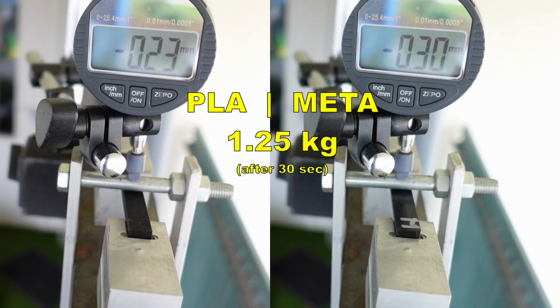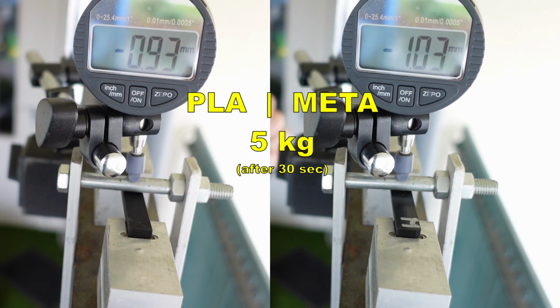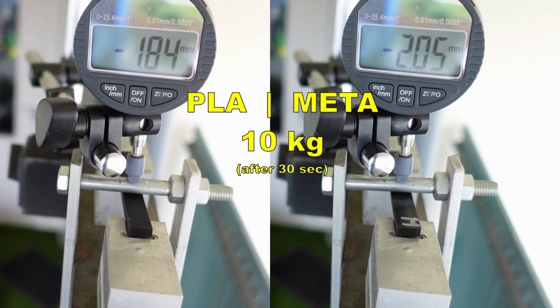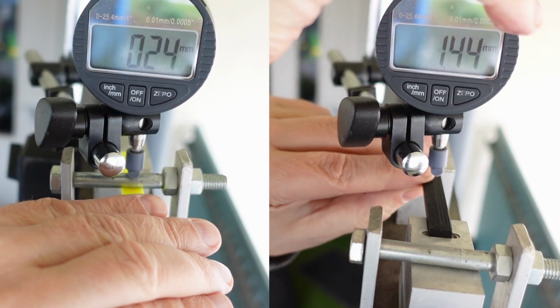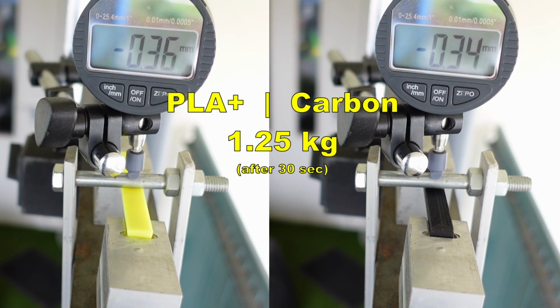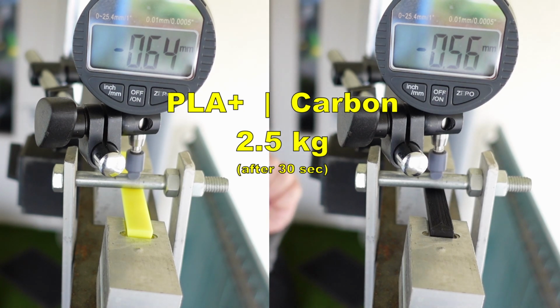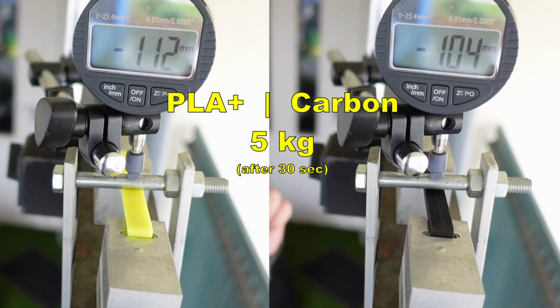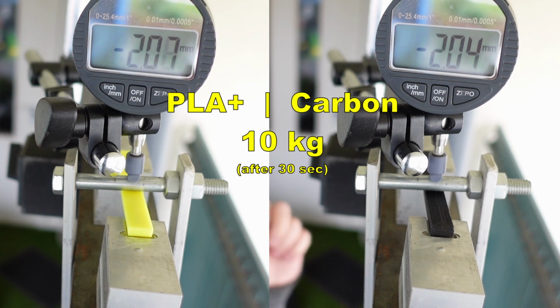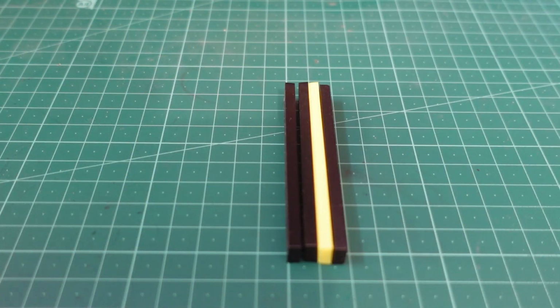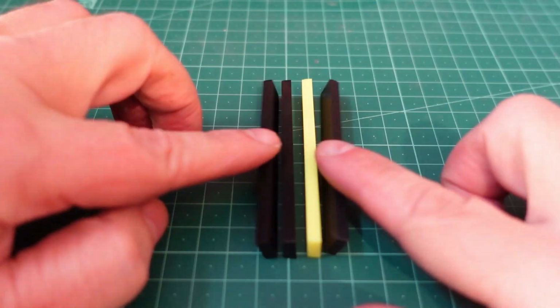Here you can see side by side the PLA and the META PLA filaments. And now this is a 1.25 kilogram load on them, and this is the 10 kilogram load. And then moving to PLA Plus and the carbon PLA, and this is 2.5, 5 and 10 kilogram load after 30 seconds. Looks like this is not too big load for this object, because I cannot see any permanent deformation on them.